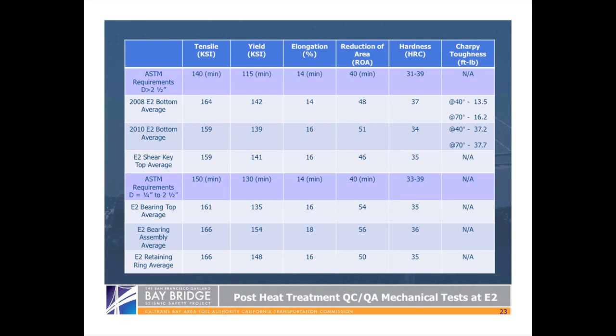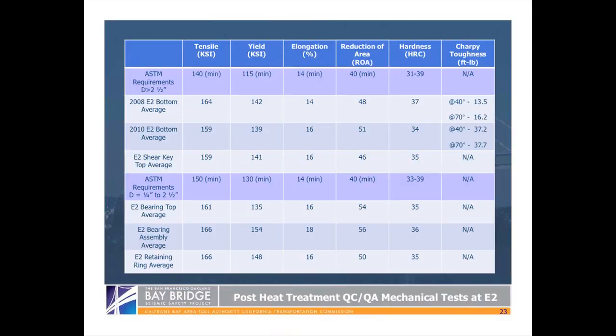And then on the far right is a new test that we have been conducting. It's a toughness test, and it's called the Charpy test. It essentially involves taking a device that's like a pendulum and swinging it into the material and seeing what kind of toughness that material has. You basically put a notch in the material so that when you swing it, you can break it. How much you need to swing it into the material is an indication of the toughness. And here again, you can see a significant difference between the 2008 and the 2010 bolts.